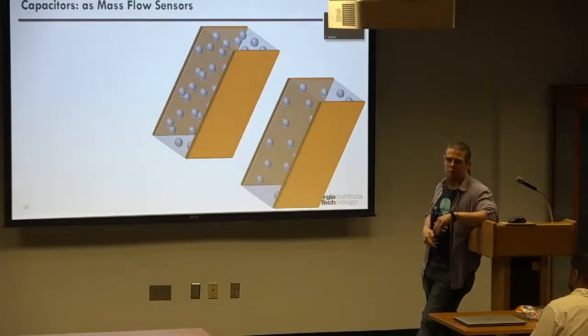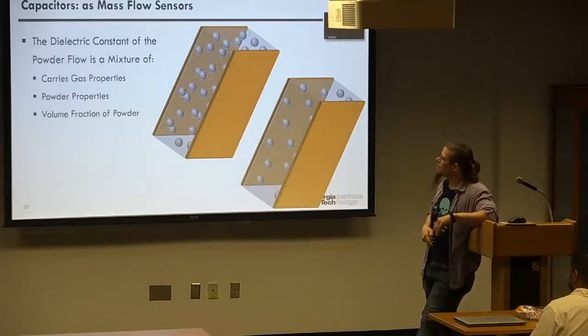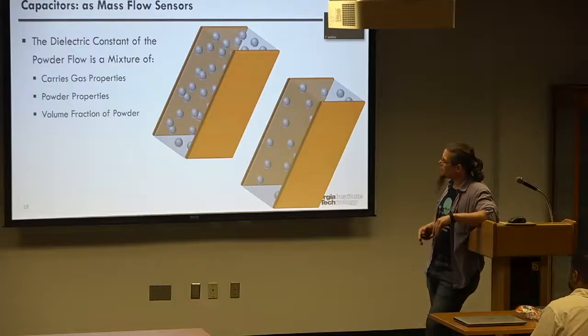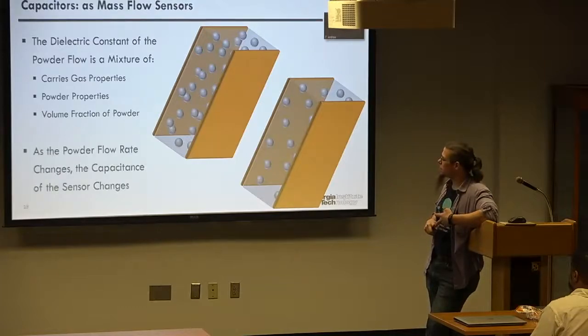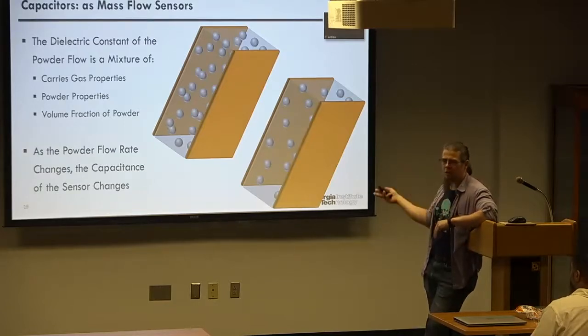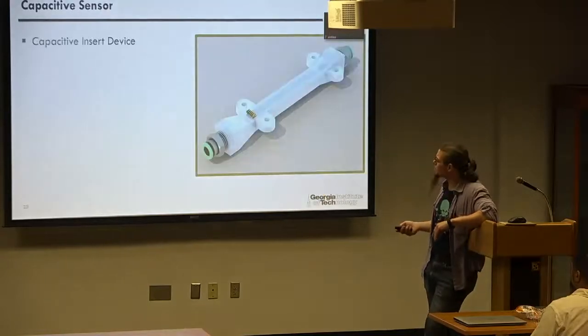We're going to put the powder between the plates. The idea here is that the dielectric constant of the powder flow is a mixture of the carrier gas properties, the powder properties, and the volume fraction of powder in the flow. So as the powder flow rate changes, the capacitance of the sensor changes. That gives us a digital signal that we can then use to feedback either for control, or we can couple it with another data stream to try and improve the error.